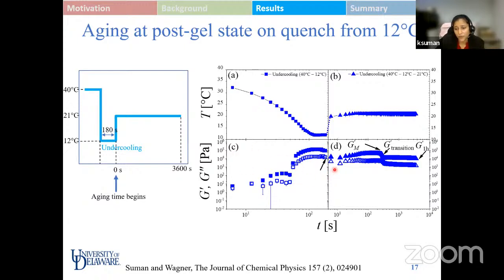After this, it is followed by a step jump in temperature from 12 to 21 degree. Since we are moving from a very arrested state to a comparatively less arrested state, we expect the modulus value to decrease, which can be seen in this narrow decrease over here on increase in temperature to 21. And interestingly, even after taking the sample to 21 degree from a very arrested state, it undergoes the similar transition as observed when we took the sample from a liquid state, which is 40 degree, directly to 21 degree.